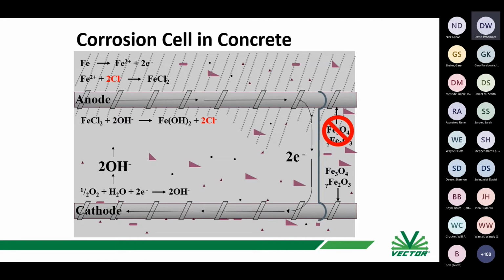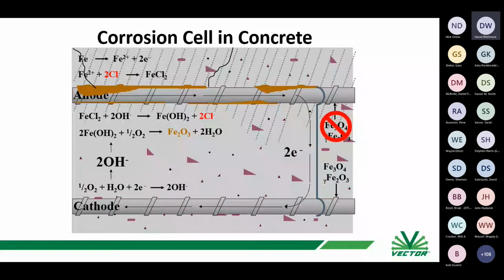Okay, no one outside of this room, and most of you in this room, care at all about what I just said. Okay. DOT doesn't care about that, whatever, but they do care that these corrosion products eventually, first of all, react with hydroxide typically because we have an alkaline material and oxygen in the environment, and we form Fe2O3, which is a normal red rust that you're familiar with. And because that material occupies more volume, it's less dense than the steel itself, that creates internal pressure in the concrete, creates cracks, creates delaminations, spalls, if you let it go.